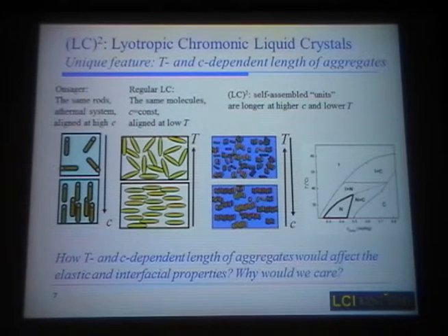All you need to cause a transition from the isotropic phase to the nematic phase is to change the concentration of the dispersed material. And if you remember that everything is based on entropy, the two entropy terms, orientational and positional, have the same scaling with temperature. So it's not going to have temperature dependence. Now, in the normal liquid crystal like 5CB, the material that we use in displays, the situation is different.